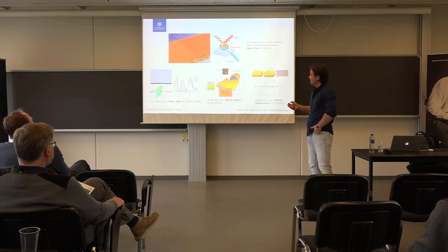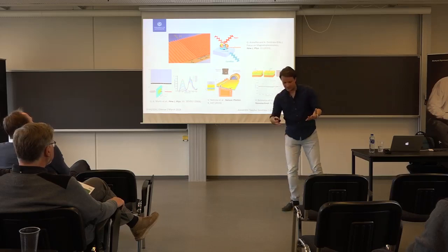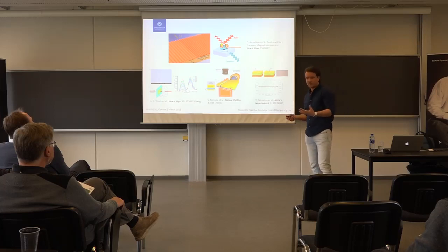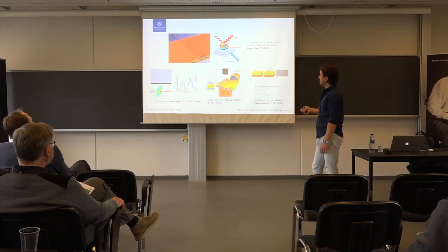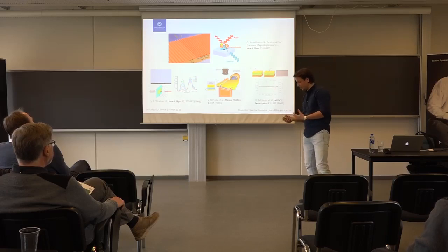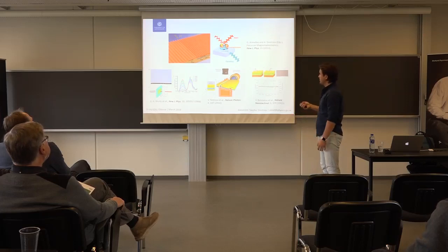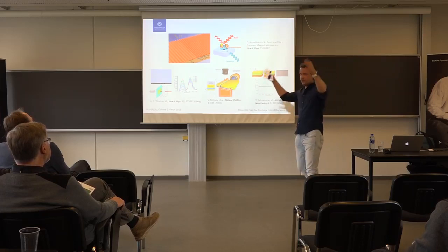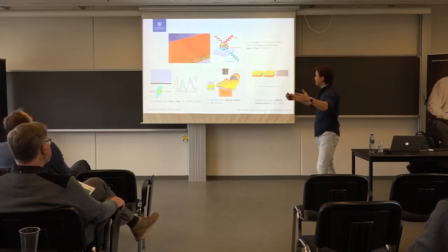But the concept of combining magnetism and plasmonics works surprisingly similar for these two types of electronic oscillations. For the propagating plasmons, you essentially change the K vector of that plasmon. For the localized plasmon, you really change how the near field looks like. The near field is how the electromagnetic field gets confined to the nanoscale from the original field of light that lands on these antennas.